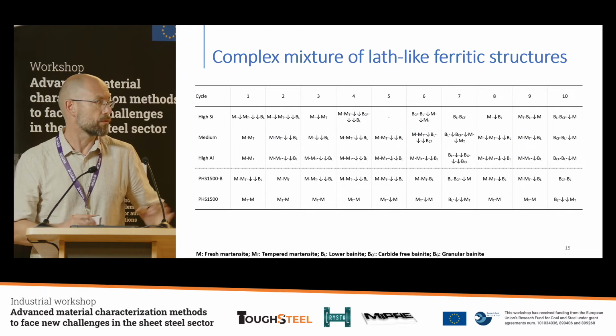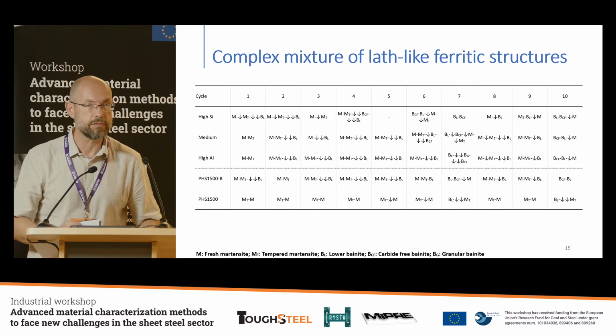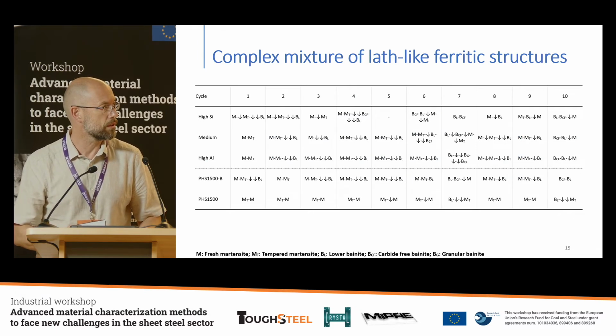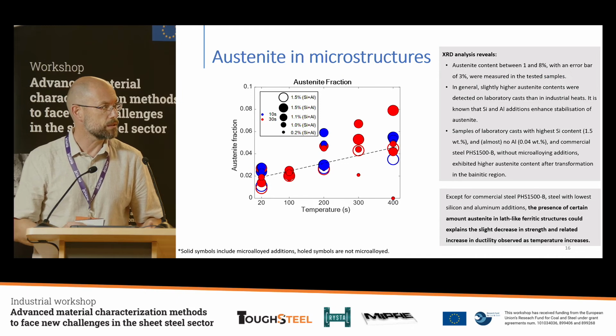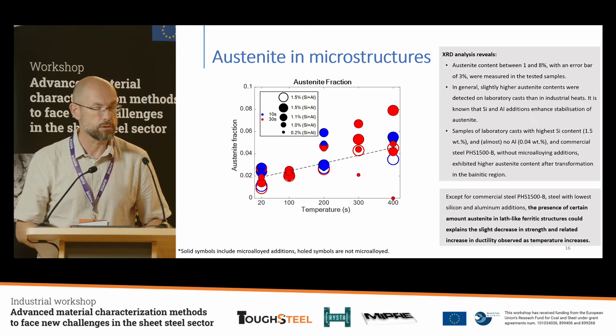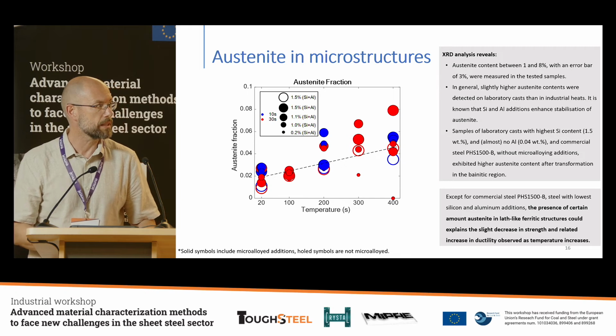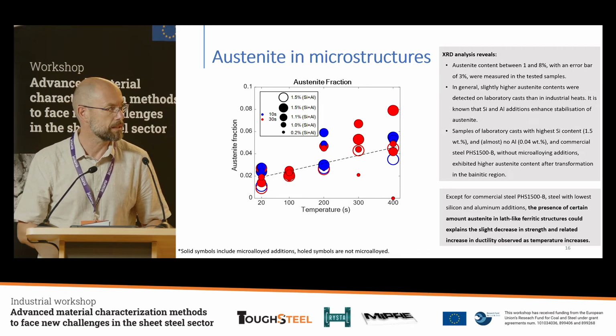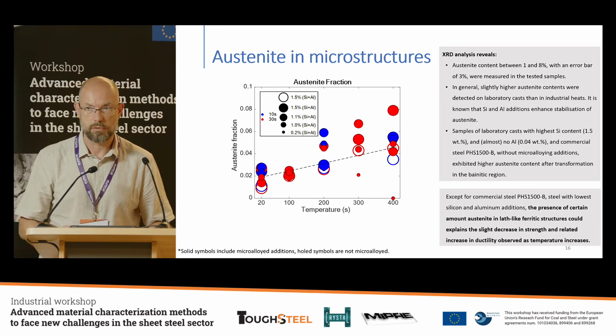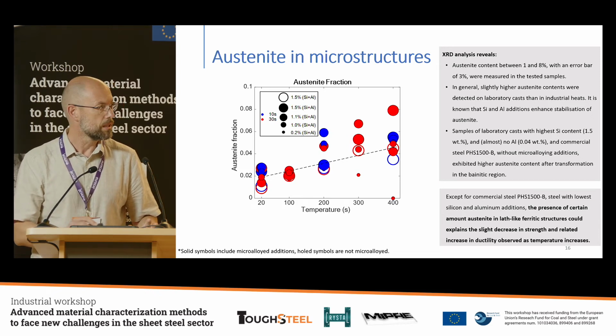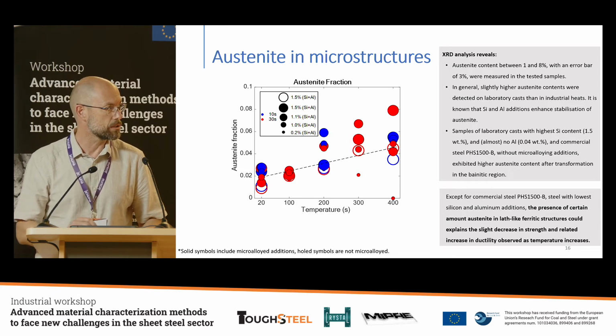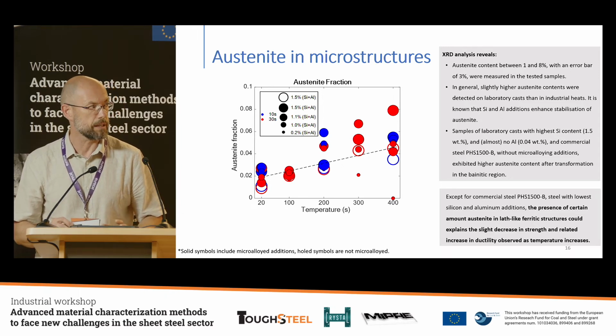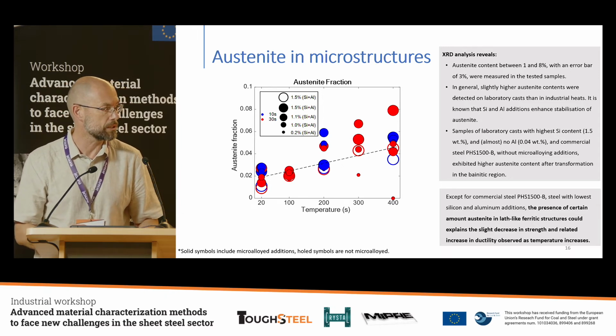And of course, you characterize the amount of the different types of microstructures for each of these conditions, and determine the retained austenite. So having in mind here, these points correspond to the 1500 steel, the experimental steel, which has no silicon, and therefore there is no retained austenite in the microstructure. So it's good to analyze the effect of the lath-like microstructure without the role of retained austenite inside the microstructure.